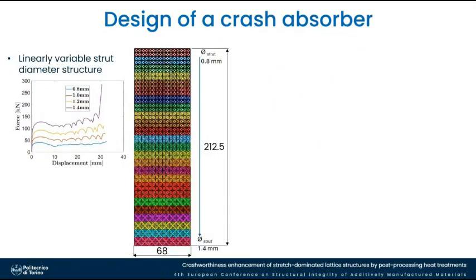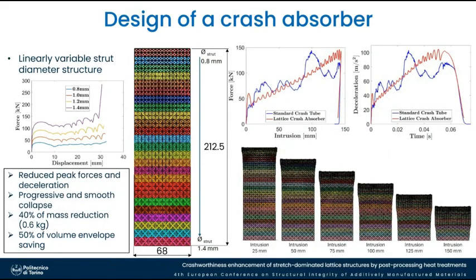And for that, through some preliminary analysis, we came to a crash absorber made in this way, where the strut diameter varies linearly from the top to the bottom, passing from 0.8 to 1.4 millimeters. This allows us to obtain basically a force-intrusion curve that increases, but also presents very small oscillations, both in the force and also in the deceleration profile, which enhances the safety of this component. The structure also presents a very progressive and smooth collapse, as is shown here.